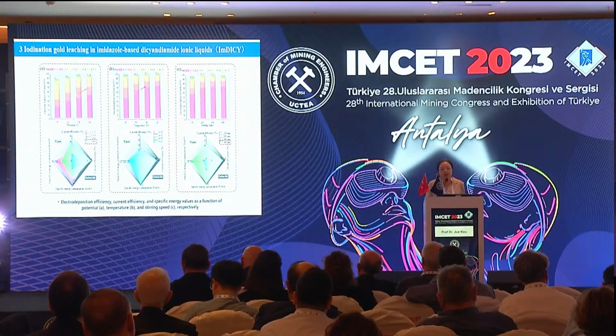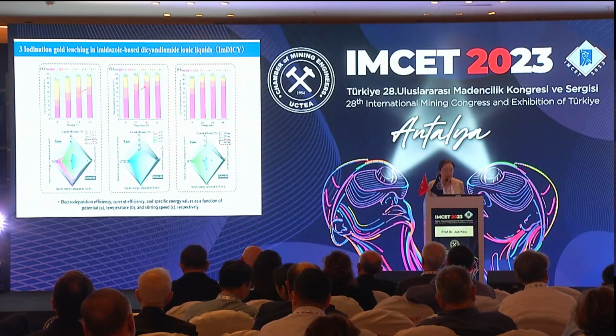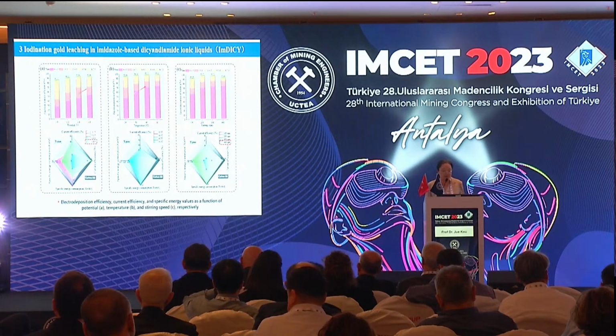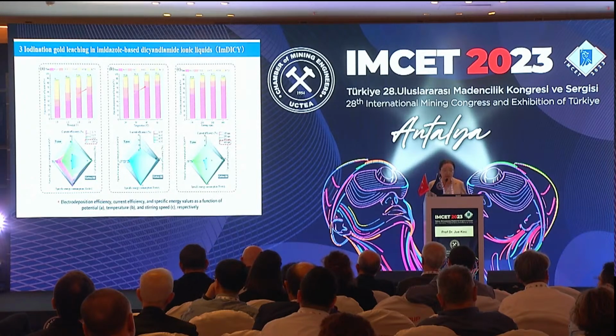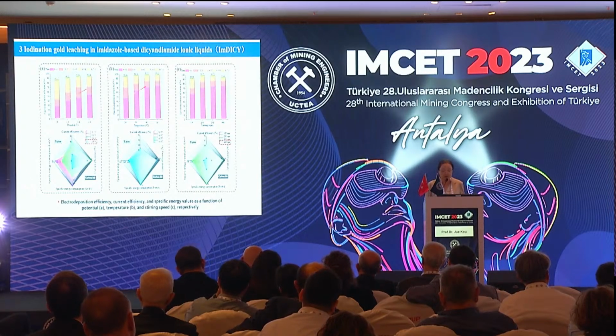And to further recover the gold from the pregnant solution, we did the electrodeposition experiments. We tested the current efficiency and specific energy value as a function of potential, temperature, and stirring speed. And here we found that the carbon felt has better performance than the titanium plate.